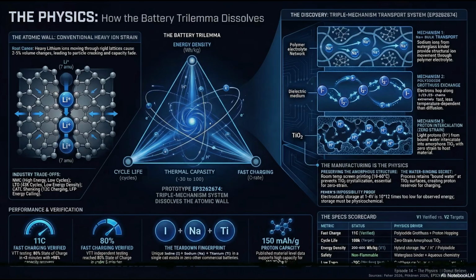And that room temperature detail is absolutely paramount to the physics. Conventional lithium-ion battery manufacturing requires extreme high-temperature sintering. They bake the electrodes in massive ovens at 400 to 600 degrees Celsius to cure them. And if you subjected this Donut Lab battery to 600 degrees, you would instantly crystallize the amorphous titanium dioxide. And if you crystallize the TiO2, you lose the soft amorphous sponge. You create a rigid, ordered crystal lattice. You bring back the Jenga tower, you bring back the strain, the cracking, the structural violence, and you completely destroy the extreme cycle life. Printing at room temperature is the only way to preserve the zero strain advantage.